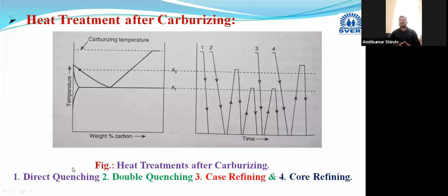Instead of providing strength, hardness, or a highly wear resistant surface, with a very light shock that material will break. And again, if the austenite at this carburizing temperature is coarse, then the ferrite at the center is also coarse, meaning the desired toughness is also not achieved.